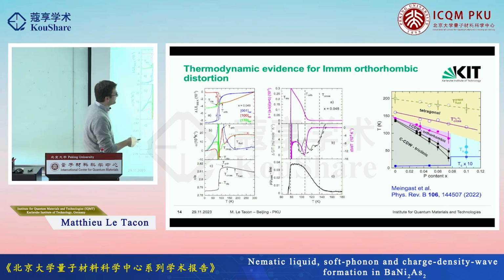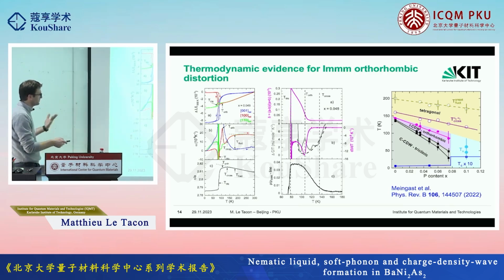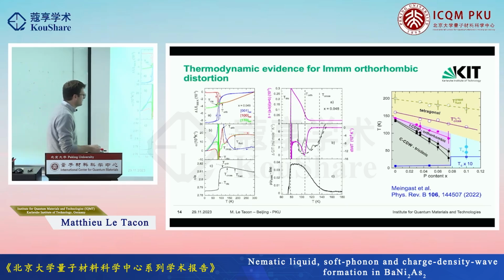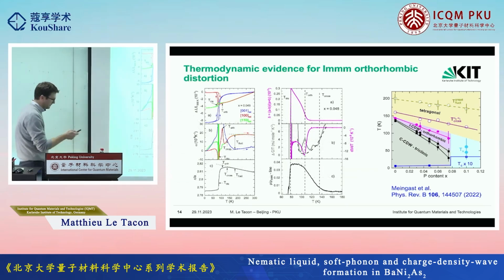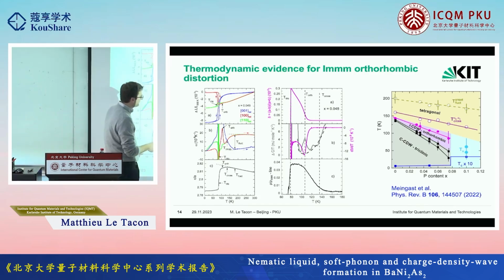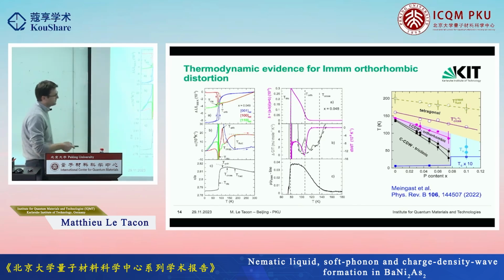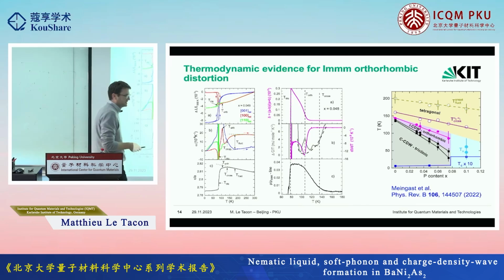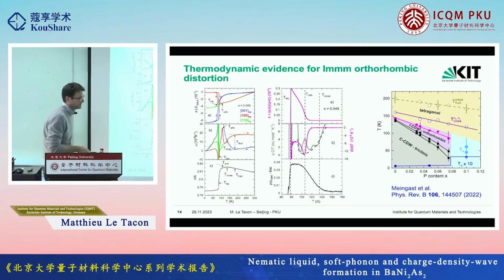You have a signature of this even in the heat capacity, so you see that it corresponds to an actual phase transition, and also in the resistivity. I'm not going to enter so much into the details here. The resistivity is actually not behaving dramatically across these transitions. No, more like a gradual change. Yeah, these are all very small changes. Frankly, if you look at the resistivity the first time, you wouldn't notice it. You have to know from somewhere else that it's there.